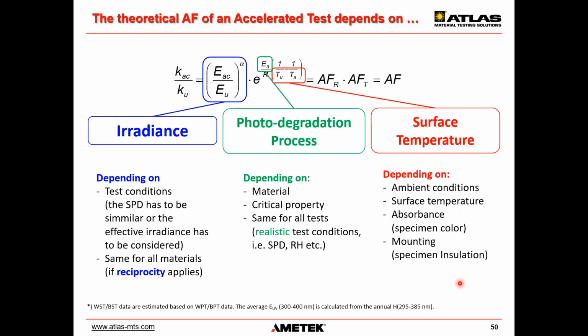Depending on reference temperature and material properties, the theoretical acceleration factor can significantly vary between different exposures. Incorrect estimation of sample temperature can lead to misinterpretation. Measuring the correct sample temperature should facilitate the comparison between different exposures.